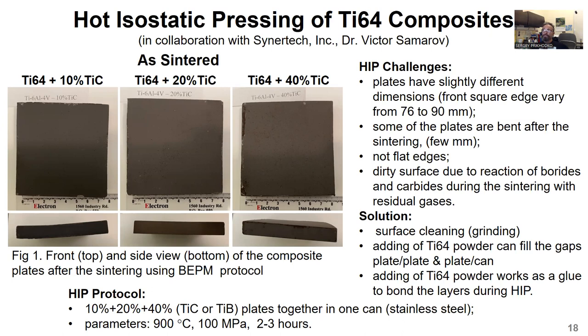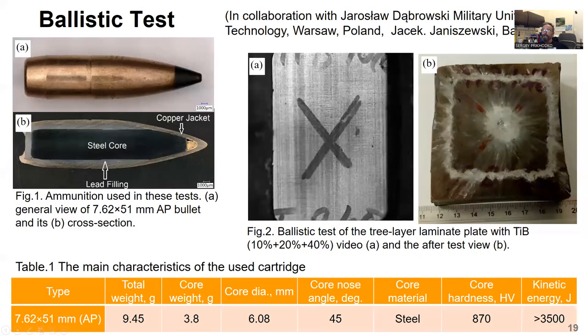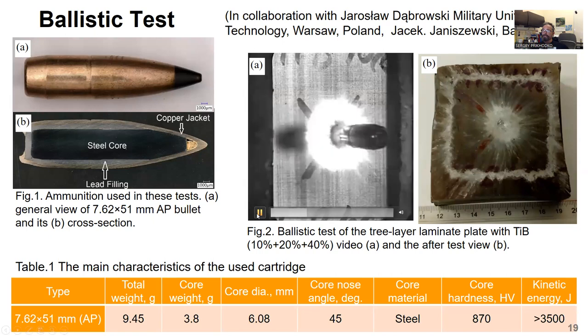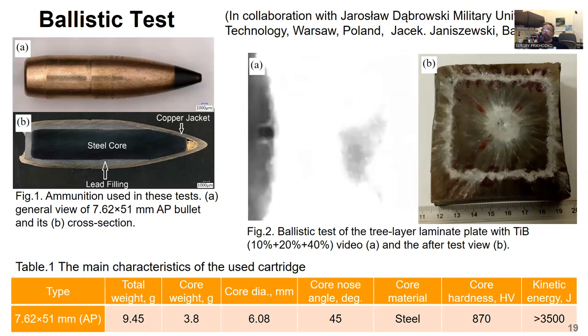Individual plates of composites with particle content 10, 20, and 40% were fabricated using blended elemental powder metallurgy. Then the plates were HIP bonded using the parameters listed here. The plates performed with stunning action. The AP 7.62 caliber bullets with core hardness 870 HV were disintegrated upon ballistic test impact, creating a very minor dent in the plate shown here on the slide.